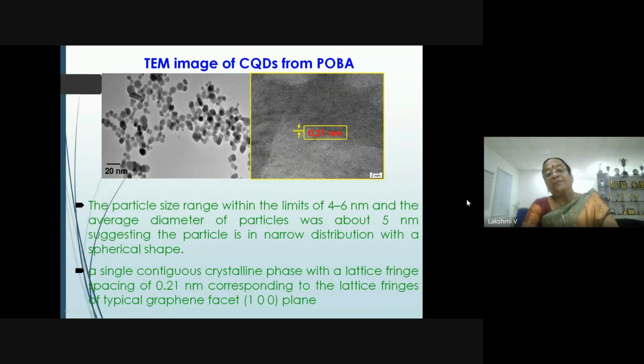The particle size ranges within the limits of 4 to 6 nanometer, and the average diameter of particles was about 5 nanometer, suggesting the particles are in a narrow distribution with a spherical shape. A single contiguous crystalline phase with a lattice fringe spacing of 0.21 nanometer corresponds to the lattice fringes of the typical graphene facet 100 plane.